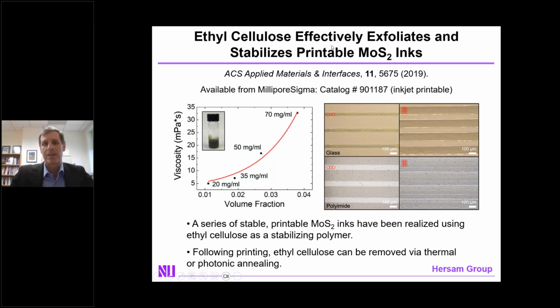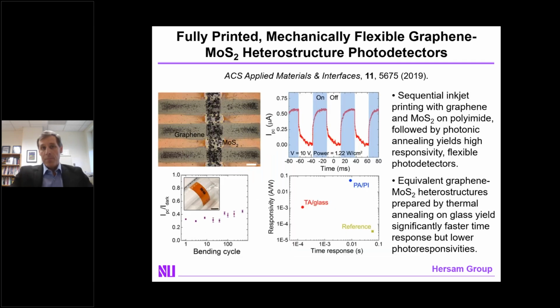Molybdenum disulfide is a semiconducting ink and therefore suitable for photodetection. And indeed, in this case, we're doing inkjet printing, and we can get very beautiful printed films and patterns without issues like coffee stain effects during drying. We then remove the ethyl cellulose stabilizing polymer using thermal or photonic annealing, giving us a conductive trace. Because these conductive traces are made out of semiconducting molybdenum disulfide, they are photoresponsive. And here I'm showing you with the light on and light off changes in the photocurrent.